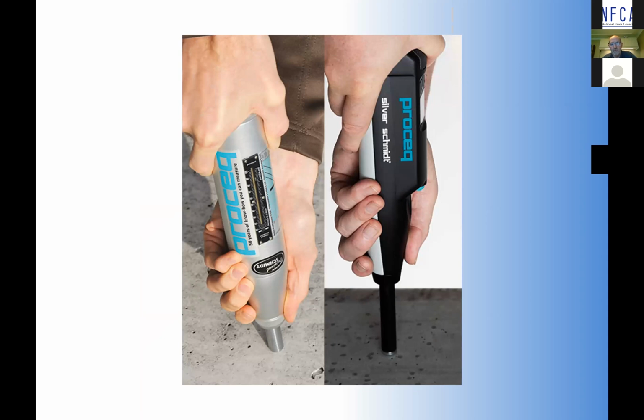And they're a pretty quick and easy pressure test, and you just push it down into the substrate, and then it kicks back into this little graph, and that corresponds to what your approximate PSI is. So rather than doing a cube test, this is another way that you can get some quick and easy approximate values. Are you dealing with 1500, 2000, 2500, 3000 PSI types of compressive strengths in your slab?